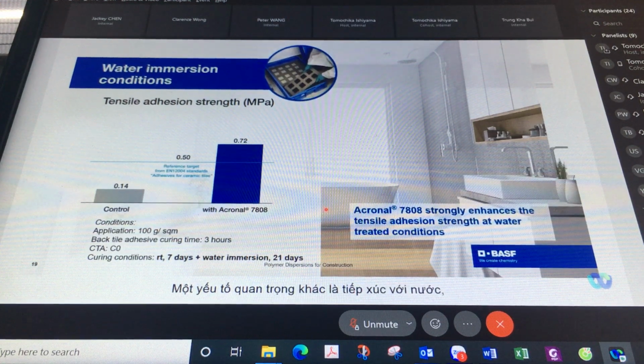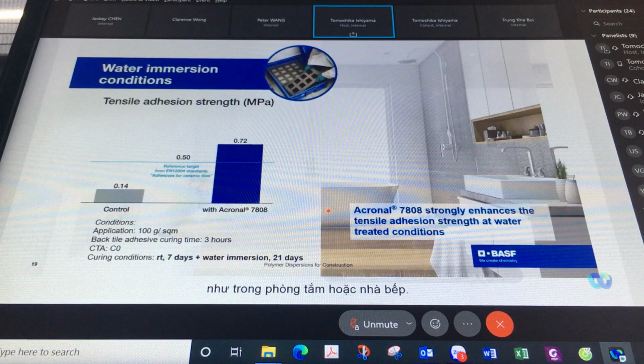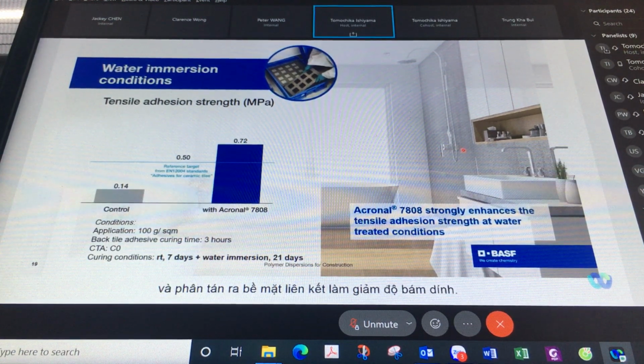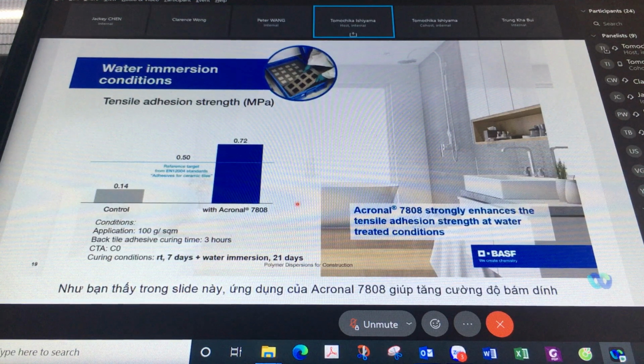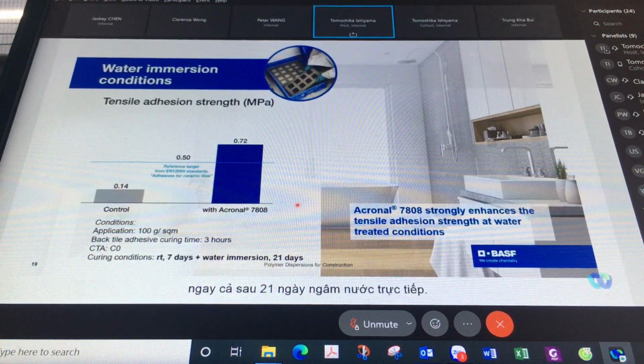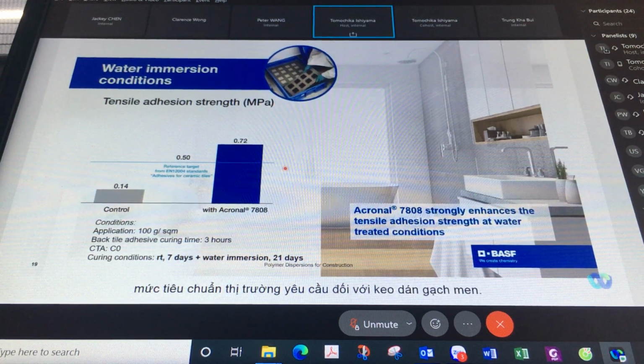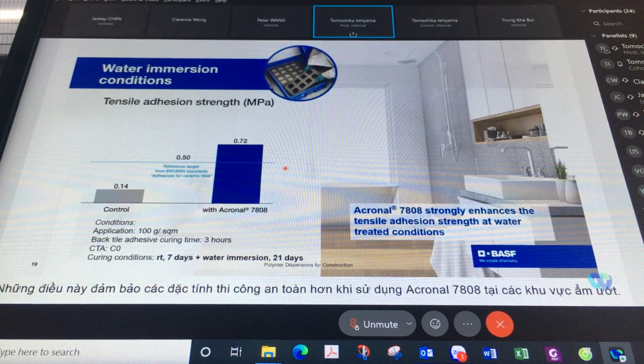Another important factor is contact with water, like in shower rooms or kitchens. The water can penetrate through the joint and spread at the bonding surface, giving lower adhesion properties. As you see in this slide, application of Acronal 7808 enhances the adhesion even after 21 days of direct water immersion. The adhesion strength is exceeding 0.50 megapascal, the required market standard for ceramic tile adhesives. This ensures secure installation with Acronal 7808 in wet areas.